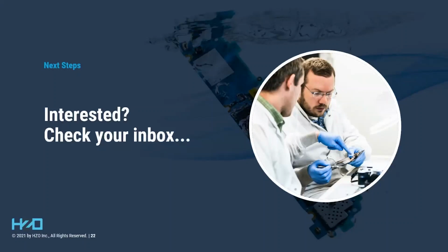So HZO has been working for a lot of years in masking and demasking, which is typically seen as one of the more expensive parts of doing a conformal coating process, particularly a Parylene conformal coating process on your product. We work at volume. We work with automation where it's appropriate. We use materials that have known performance characteristics. So we source our masking materials in such a way that we don't have to use too much of them in order to get the adequate masking. Couple that with the ability to automate the application, automate the inspection, and that drives a lot of the cost out of the masking and demasking of a product.